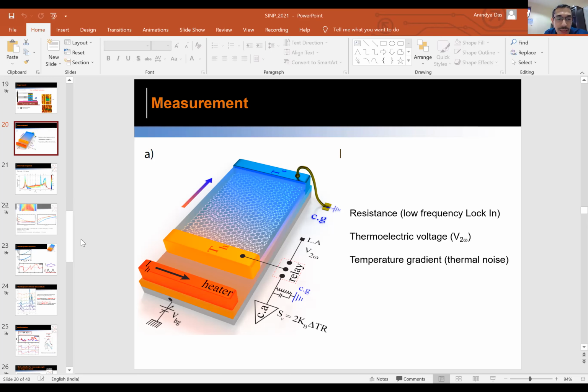This heater line is bigger than this size. This is like 5 to 6 micron. The heater line is quite big. So it's sort of like a 1D system, although the system is like a 2D, but there is no temperature gradient across this axis. It's almost along this X axis. So along this there is uniform temperature, like the color has been shown. As a result, it's very close to a one-dimensional model. And if you solve a one-dimensional model with Fourier's law, it will give you the linear profile.